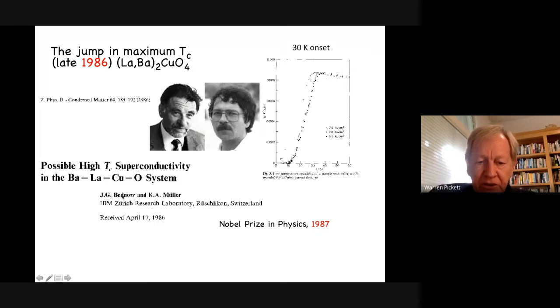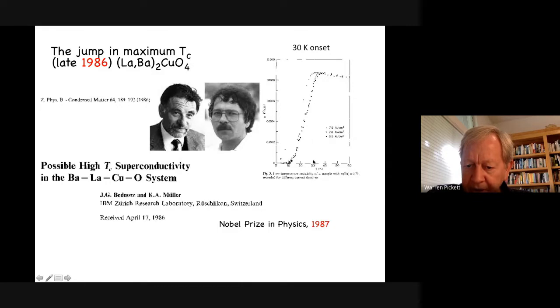George Bednorz and Alex Müller at IBM Zurich. Here is the data. It's not very impressive data, but the resistivity starts to go away at 30 degrees Kelvin. And within just a few months, other workers cleaned up this material. It's a lanthanum barium copper oxide system.